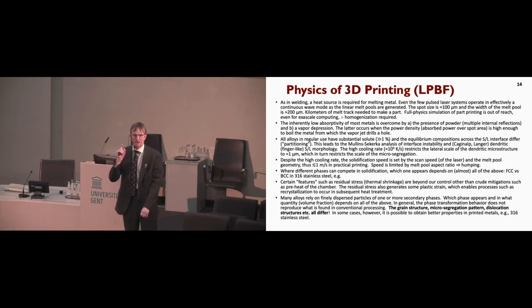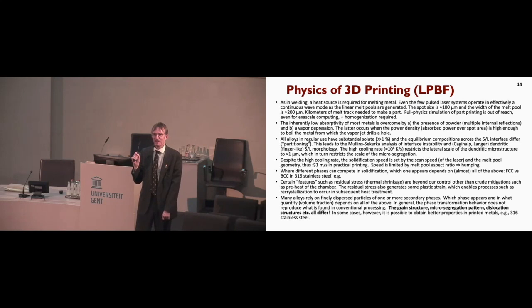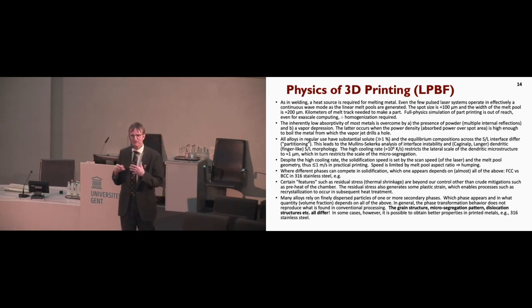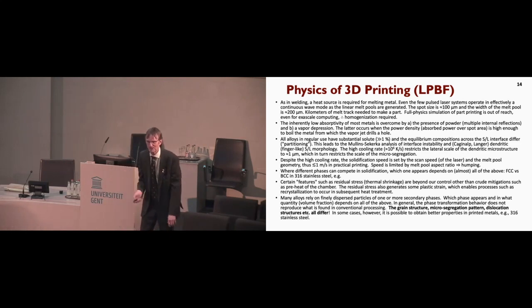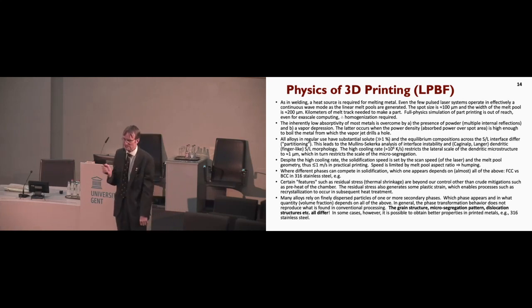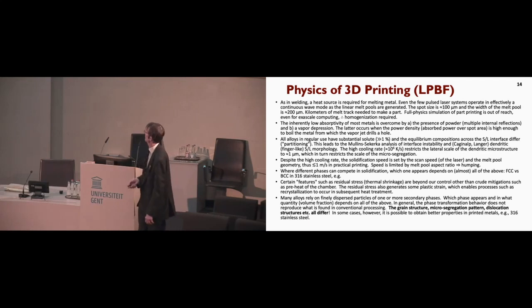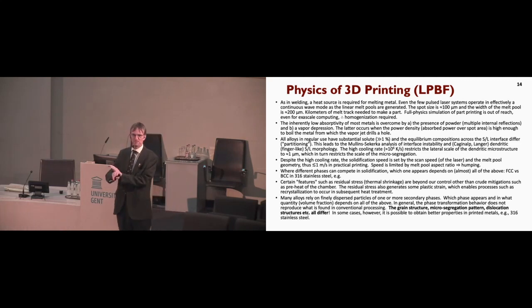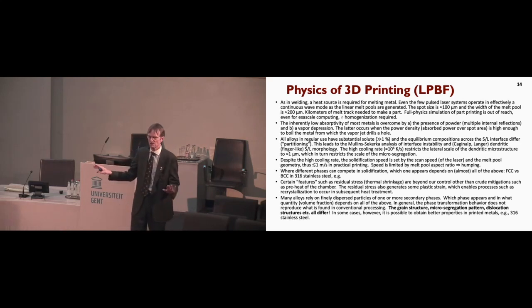And I'm going to illustrate the point that I made some fairly basic errors. So, for example, remembering all that had been done in rapid solidification and noticing these estimates that the cooling rates can be as much as 1,000,000 degrees per second, I found myself thinking, oh, well, this must be such that it eliminates microsegregation. And it turns out that despite the high cooling rates, then the actual speed, sorry, let me stop that cursor from moving around.